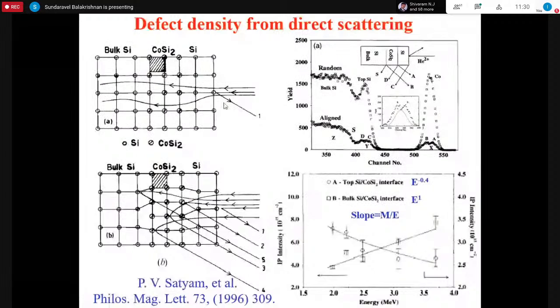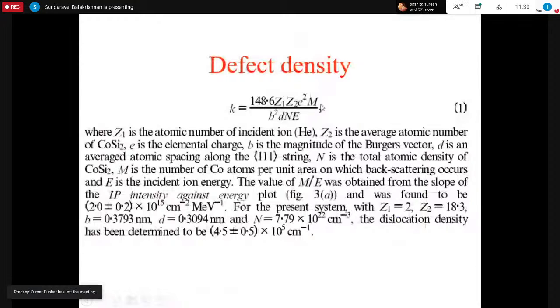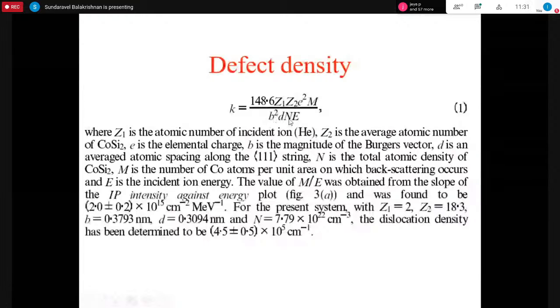In cobalt disilicide, from direct scattering, we have studied the type of defects. I told that from this channeling, interface peaks A and B are there, and we can extract these peaks. For example, whatever is shown in the inset here, we can extract this peak A and peak B area. From that, we can find the number density of cobalt, and how much of it is coming from the interface peak as a function of energy. If you plot, you get these curves, and the slope gives m by E. This m by E value you can put in this expression, where b is the Burgers vector, n is the atomic density, and d is the distance along this axis. From this, you can find the defect density.